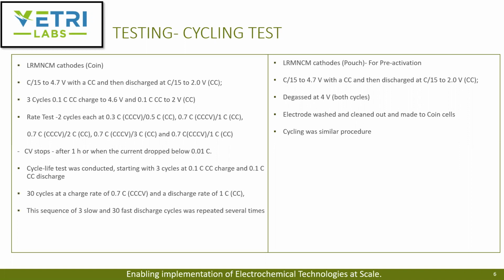For the pre-activation cells I talked about, they have a pouch cell and do the activation step, going to 4.7 volts, which is done only once. Then they discharge, and degas around 4 volts at both cycles, and the electrodes now contain all the decomposition products and organic products that are formed.